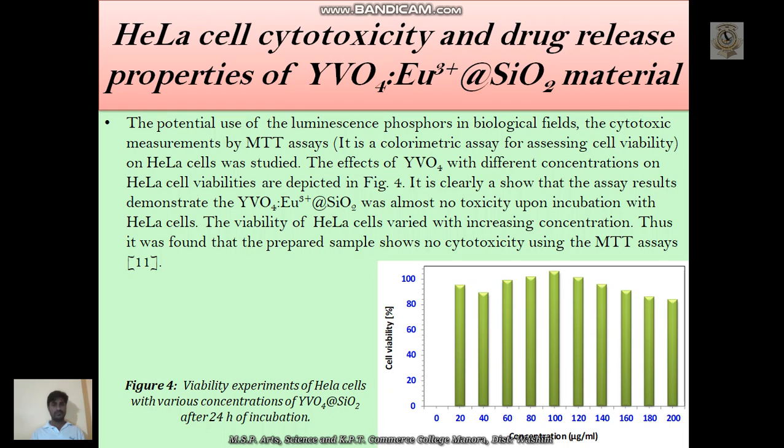This is another characterization of my research work: HeLa cell cytotoxicity and drug release property of YVO4 capped with SiO2 material. We can see in this graph that by varying the concentration we can measure the toxicity. It is clear from the figure that the assay results demonstrate that YVO4 capped with SiO2 shows almost no toxicity upon incubation with HeLa cells. The viability of HeLa cells varies with increased concentration. Thus, it is found that the prepared samples show no cytotoxicity using the MTT assay.